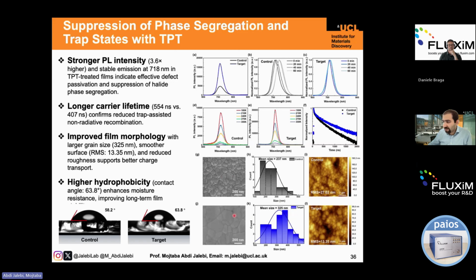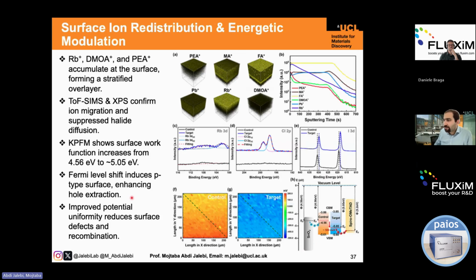As evident from these SEM images, from control to the TPT approach, we have reached a larger grain size, and also a smoother surface. You can see the surface roughness is significantly reduced in the TPT. And in terms of the hydrophobicity, the contact angle, you can see we have a higher contact angle for the target film. That means we have enhanced the moisture resistance of the perovskite thin film as well.